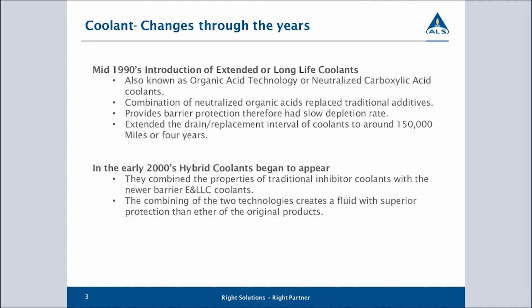There was a lot of interest in these coolants when they first arrived, because there's a lot of hassle in looking after cooling systems, and this certainly took away a lot of the hassle factor. However, these coolants didn't seem to work out as well as expected. We did find corrosion was still occurring in engines using these coolants, and in some cases you would even have accelerated corrosion, more serious than what we had seen on the conventional coolants. This was eventually attributed to a number of factors, but one of the main ones is that the barrier that forms from the organic acids can be disrupted, particularly if there's vibration or aeration occurring in the system.